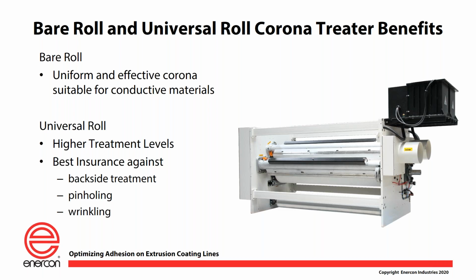The universal roll that I mentioned before is our ceramic electrode with a proprietary covering on the ceramic roll, and it allows us to get higher treatment levels, to keep the footprint of the station smaller, and it helps against getting backside treatment, which usually occurs when you get air behind the web and you ionize the backside of that web. It helps avoid pinholing, and it helps reduce wrinkling.